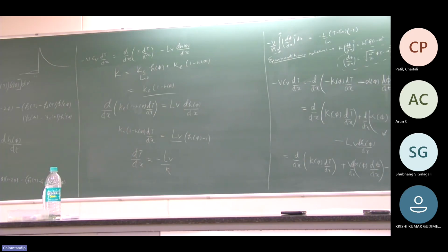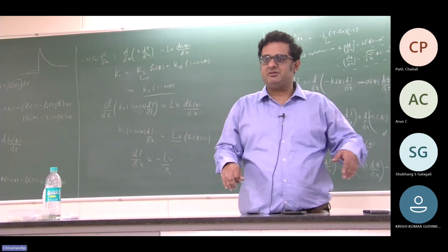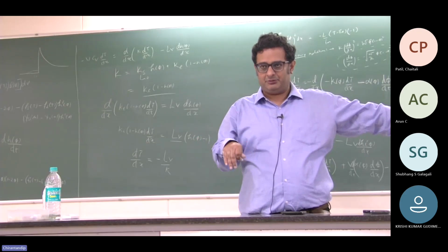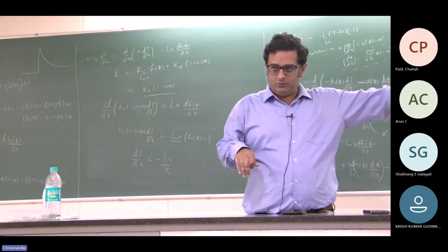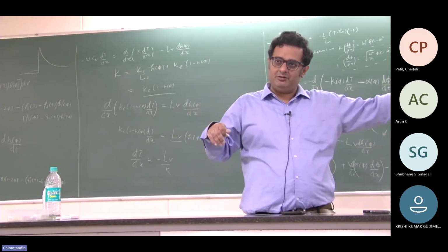But you must write the right model. If you write the WBM model, there's a problem. In the WBM model, inherently, there are other effects coming in, which will not allow you to take this, because the structure of the interface itself is a function of the sum of the effects. Whenever you do all of this, it will not be one single expression. Every time you change the sum of the effects, the equilibrium will change.